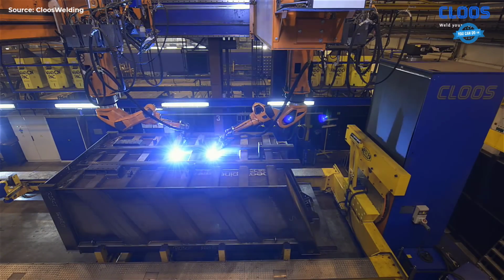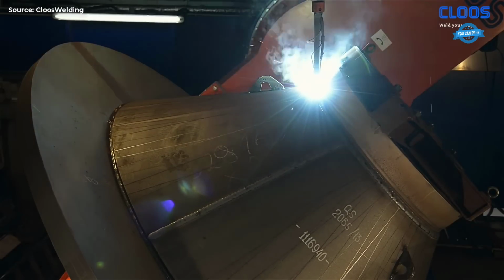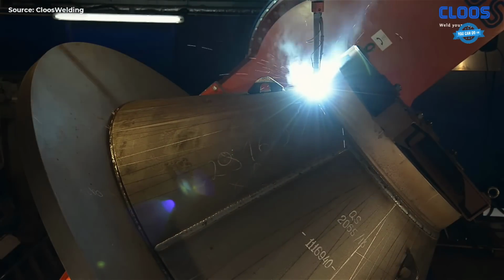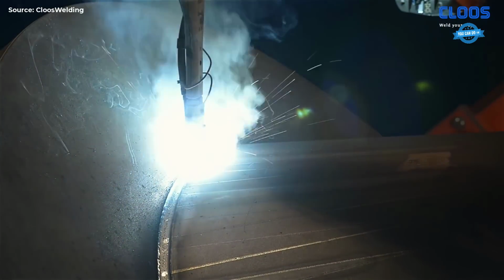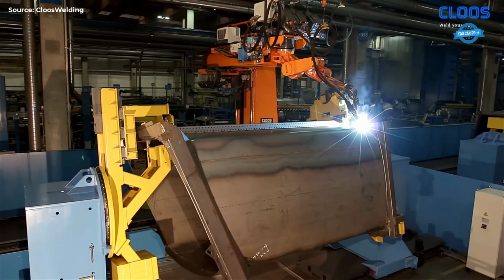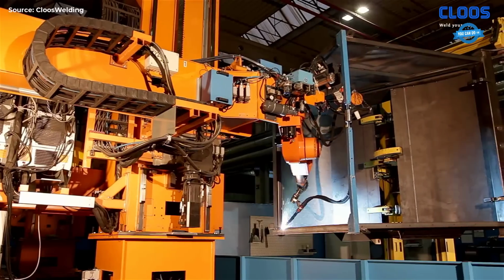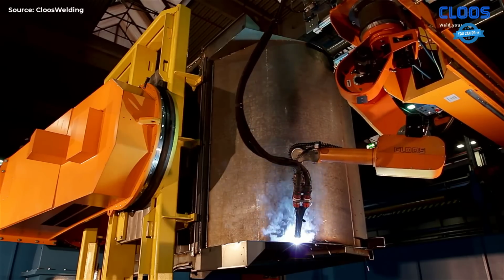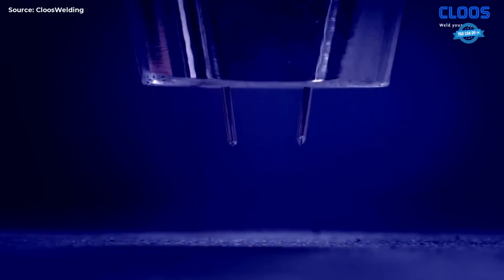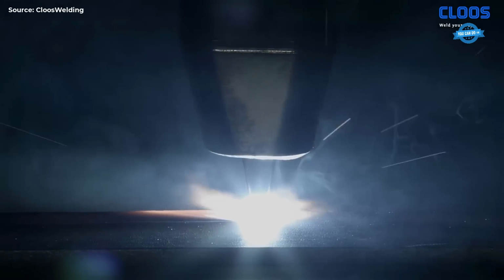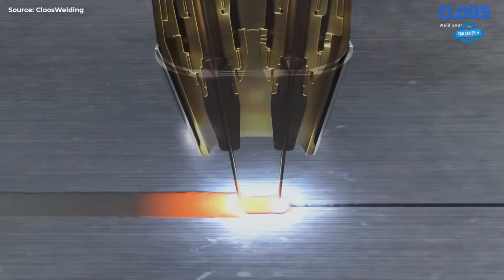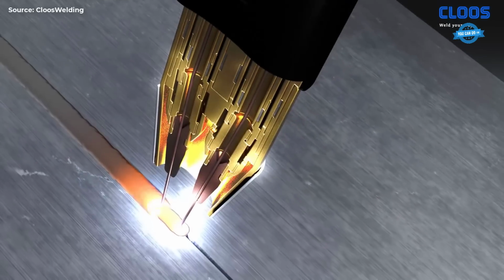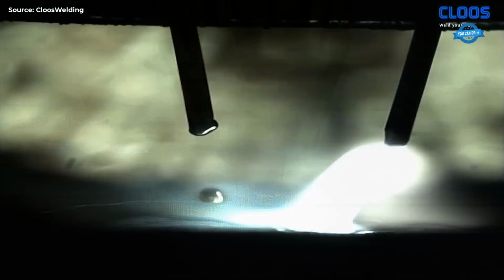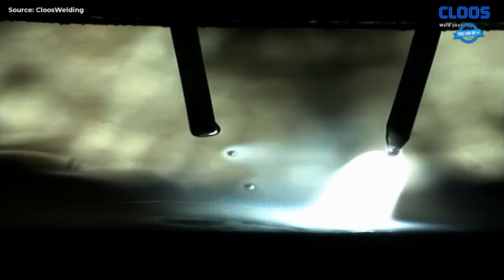In the tandem weld process, 2 arcs burn in a common molten pool. Tandem weld is characterized by 2 electrically separated processes which match each other perfectly. This possibility opens up a multitude of combinations. The front wire ensures a safe penetration. The back wire quickly fills big joints with filler material. The high deposition rate results in weld speed and in volume filling. Therefore, tandem weld is suitable for thin and for thick plates.